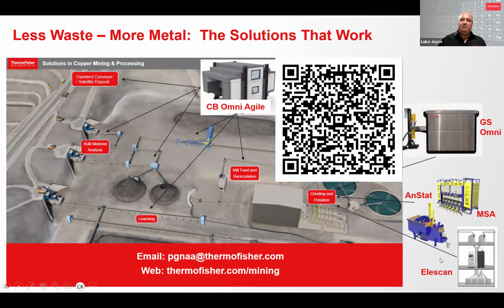Can I just add one more comment there, John? In the case of the analyzer we have up at Red Chris, each truck that dumps its ore, what's considered ore that's been sent from the mine to the plant, one truckload of material, once that's gone through the crusher and then onto the conveyor belt, equated to about 6 minutes or 1 kilometre of material stretched out over that belt. That was equivalent to one truck. So we're measuring that rock from that truck in real time. With the blasting, the haulage, the crushing, sometimes people think that all the variability gets blended out, but in that 6 minutes we were providing minute by minute analysis. We could see variability within each truck, so that highlighted that even within one truck there's potential to segregate and divert low value material that's within a truck that on average is above grade, but there's actually a low grade opportunity to divert.